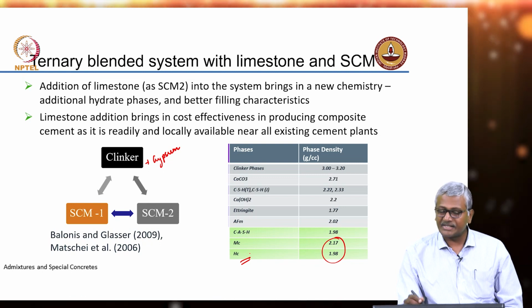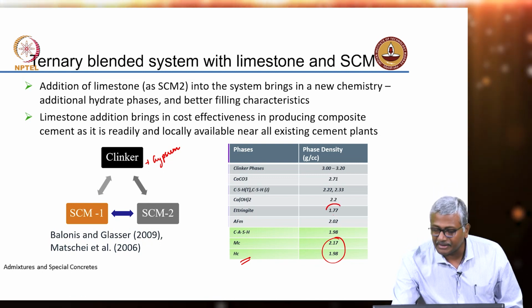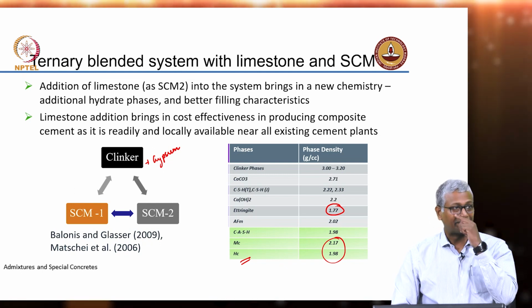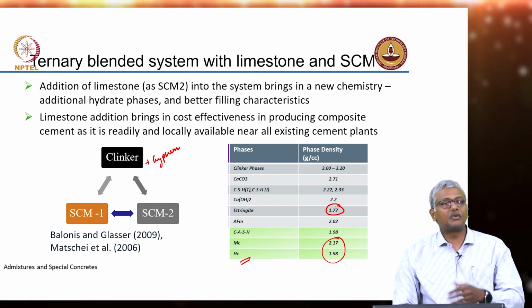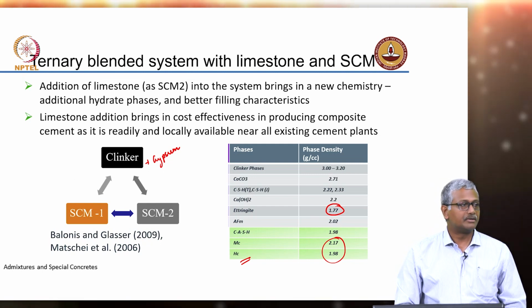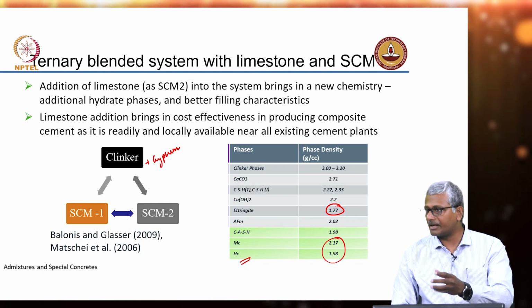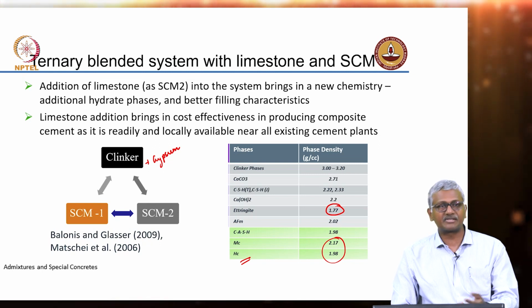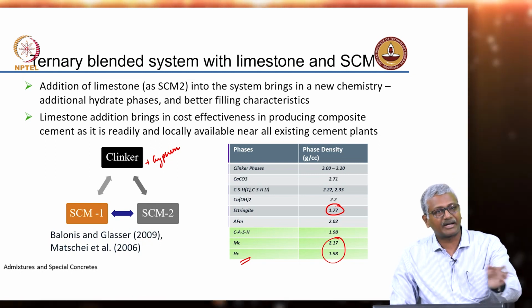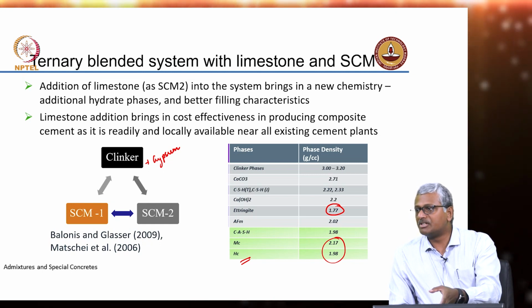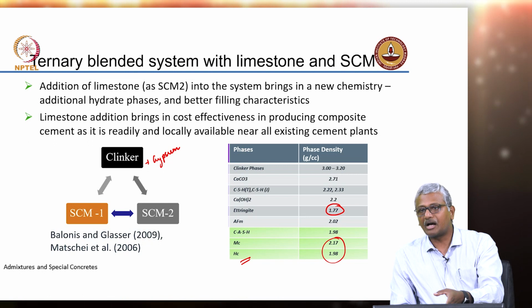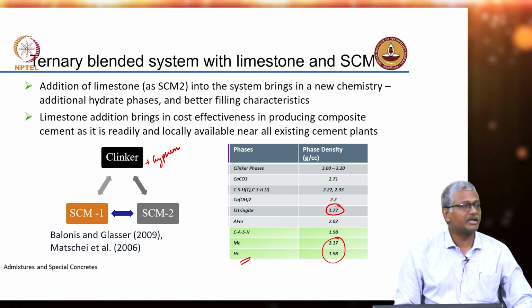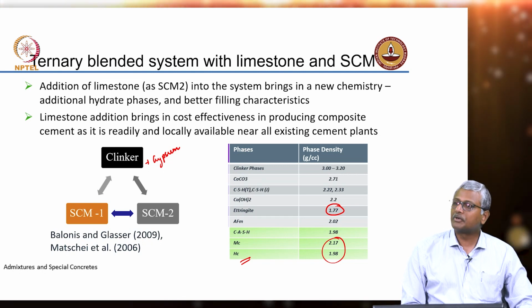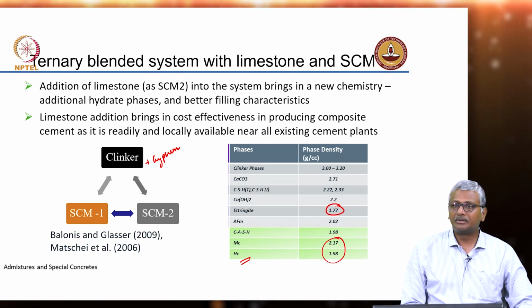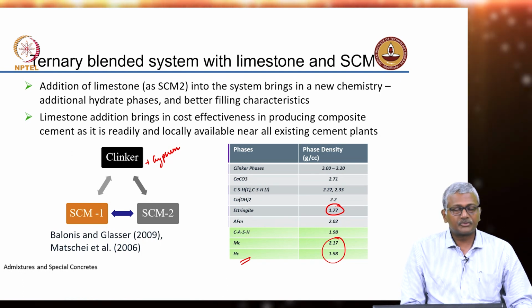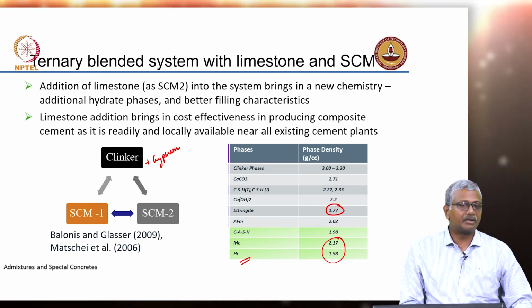But interestingly, what also ends up happening in this system is that the ettringite that is forming early stabilizes. Why should that stabilize? How is ettringite formed? Because of aluminate and sulfate reacting, right? Aluminate and sulfate react to form ettringite. But in normal Portland cement systems, there's a lot of aluminate available. So that aluminate interacts with ettringite to produce monosulfate. But now I've introduced a system where I have carbonate also present, and this alumina wants to combine with the carbonate and start producing monocarbonate or hemicarbonate, leaving the ettringite free. So what will happen to the ettringite? It will remain stable in this system.